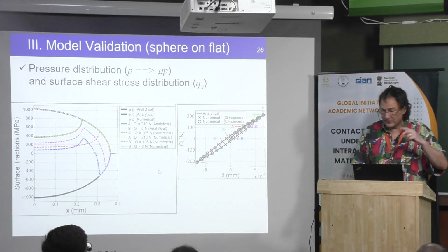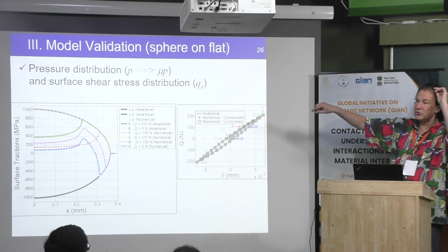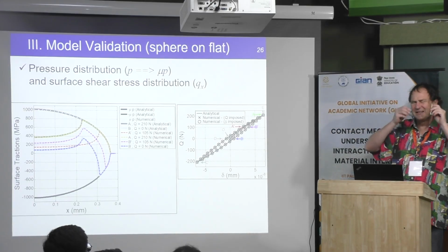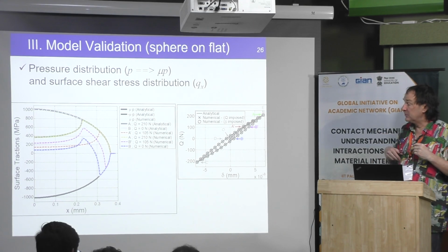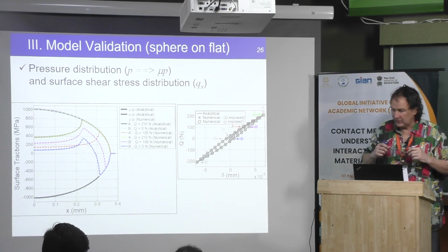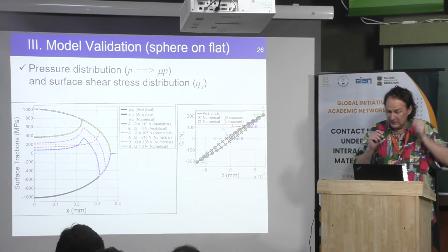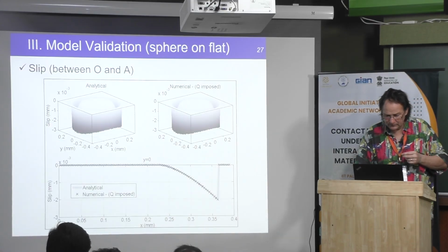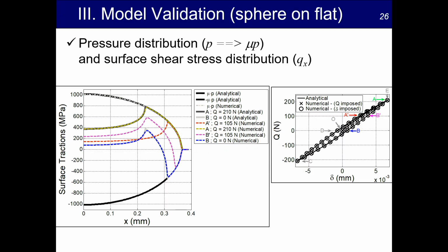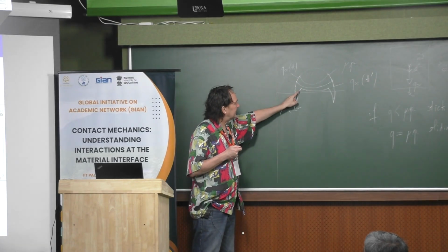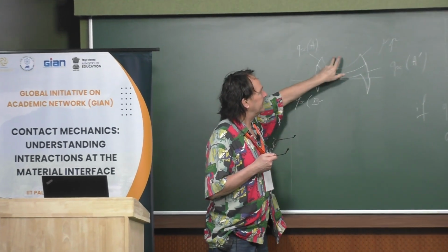Okay, then we are speaking about the shear stress distribution during a fretting cycle, for stick slip. Then you have that in mind. Now also, this is a view of the shear stress. Now we can have a view of the sliding. Remember that at the border we have some sliding. Here this is sliding, here this is sliding, and in the center here it is sticking.